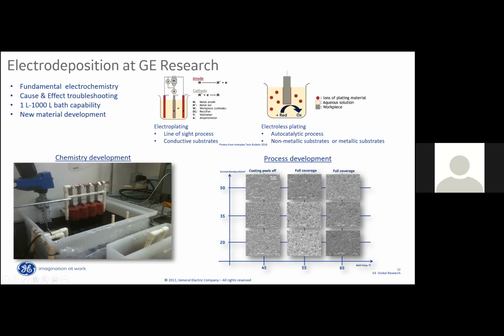And I do want to just show, this picture doesn't mean much, but this is a typical 250 liter plating tank that sits in my lab. And I wanted to show this example of how we develop process. So there's bath temperature on the x-axis, there's current density on the y-axis, and you can see how our coating morphology is completely different by tweaking all of these parameters. So we routinely do both chemistry and process development here on site.